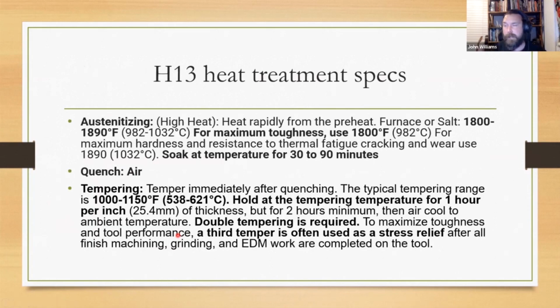And just to emphasize that, like I said, you can get a data sheet on all of these tools, on all steels. This is right from a tool steel manufacturer. Bringing this up to critical temperature, look at this range, 1800 to 1890. Well, first thing that you need to notice is that that's a lot higher than what was shown on that earlier chart. That's really, really hot. You can do as low as 1800. It says air is the quench, meaning air is sufficiently, and this is why that chart, getting back to what Victoria said, sufficiently rapidly is the wording, because there's different rates of cooling that you need for different categories.